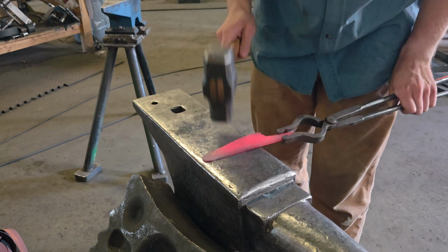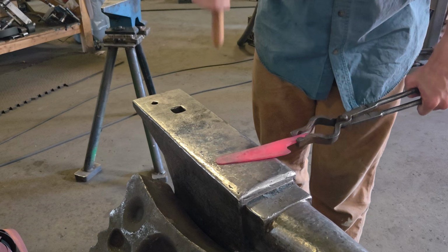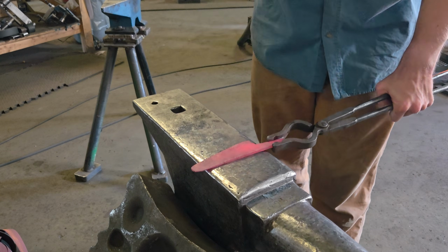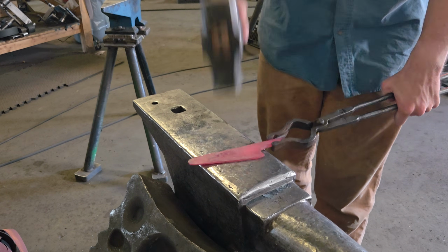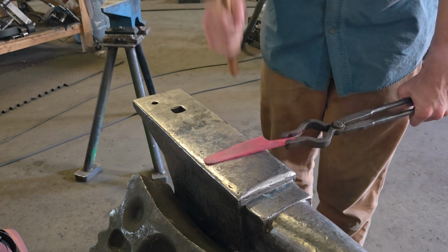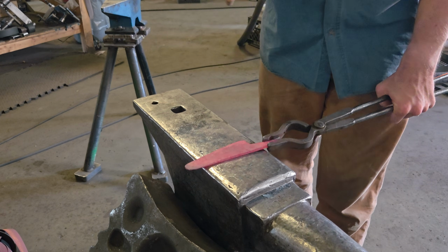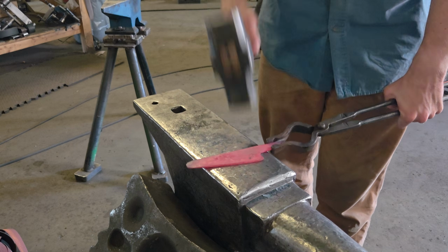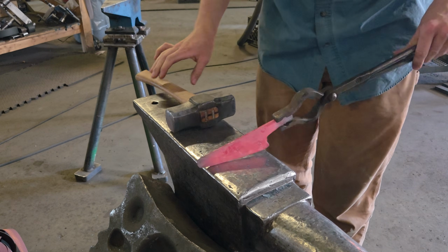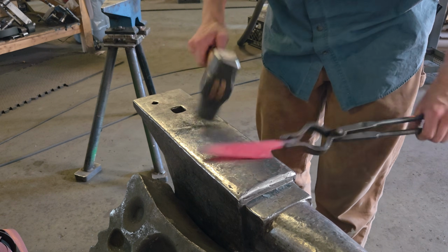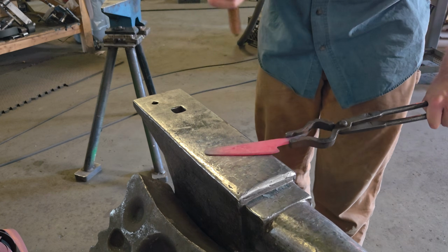It's also very important when you're forging to forge symmetrically. You want to keep even stresses in the blade on both sides. So switch over and hit each side of your blade. Don't do all your forging on one side. Otherwise, you could end up with a lot more warps and other stresses that can cause cracks. So you don't want that.